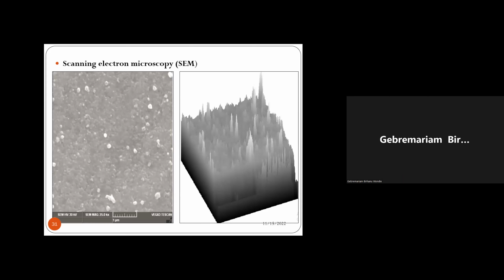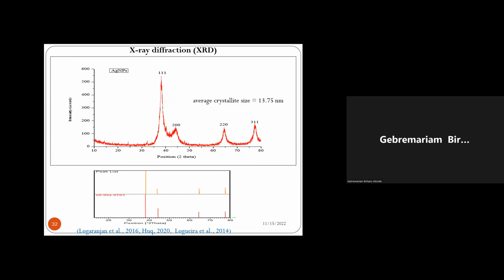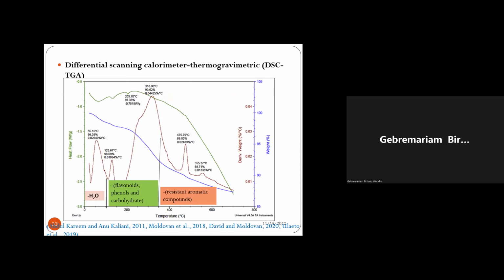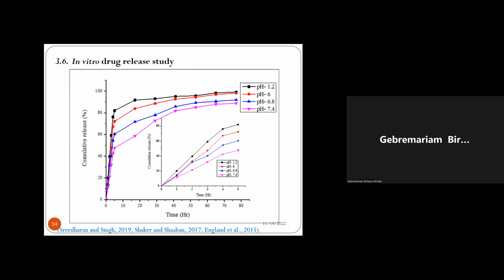Thank you. So SEM analysis also indicated successful loading of the silver nanoparticles, and X-ray diffraction also shows the average crystalline size of the silver nanoparticles, and the differential scanning calorimetry (DSC) analysis of the silver nanoparticles also gives different graphs indicating the successful loading.